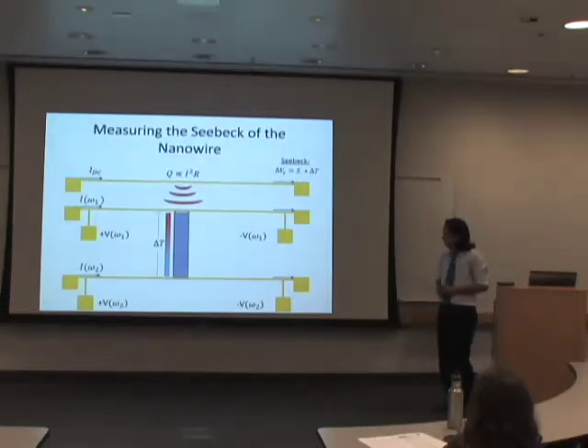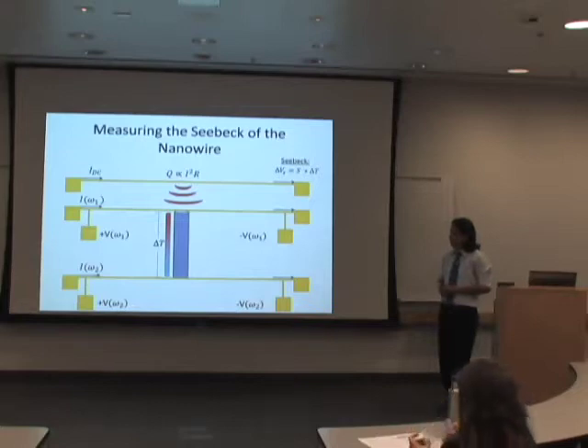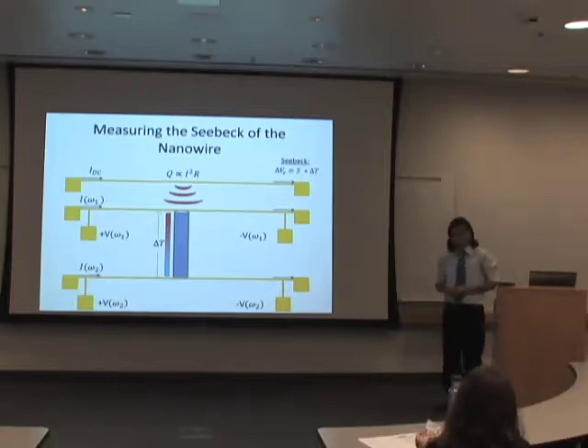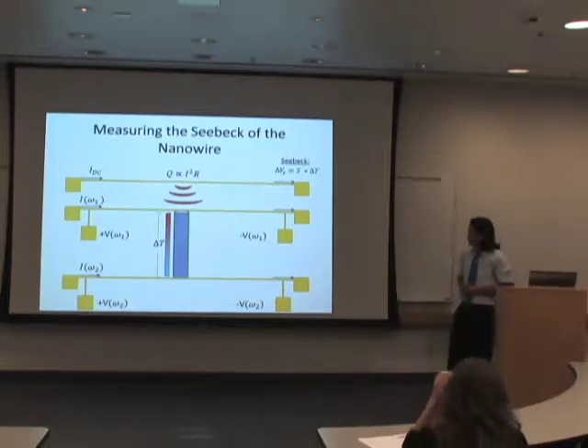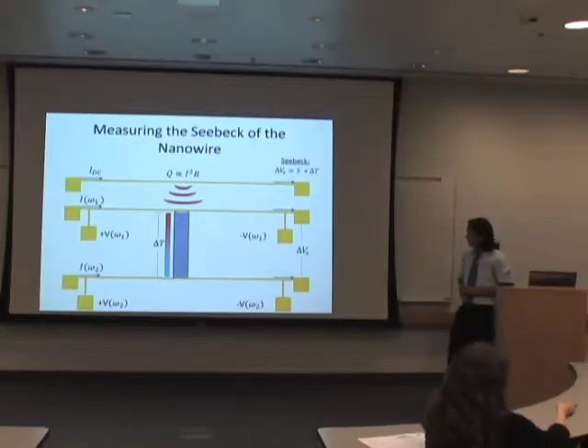So going back to our diagram, we need to measure how much difference in temperature there was before and after we apply the heat source. For that, we need accurate resistance measurements. And again, we use a 4-probes configuration. We run current through the outside probes, an AC current with very low current, because we want to avoid this Joule heating here. So we want to use very low currents. And we measure the voltage drop at this frequency only to get rid of the noise. We do the same on the bottom line, and calculating the difference in temperature in each line, subtracting from each other, we get the difference in temperature. Finally, to measure this Seebeck voltage, we measure the difference in voltage between these two probes.